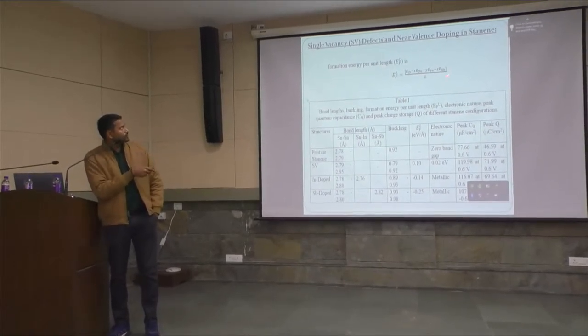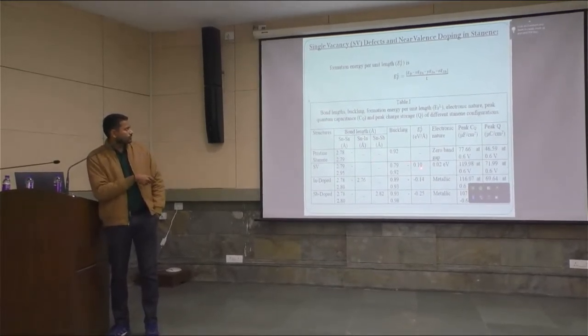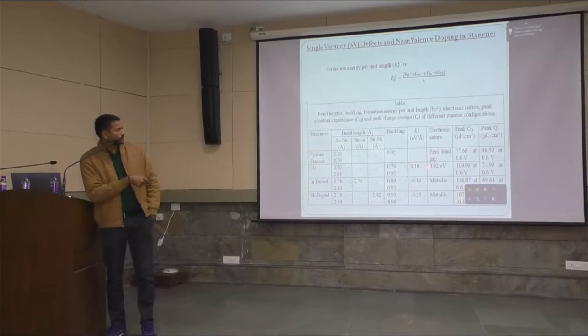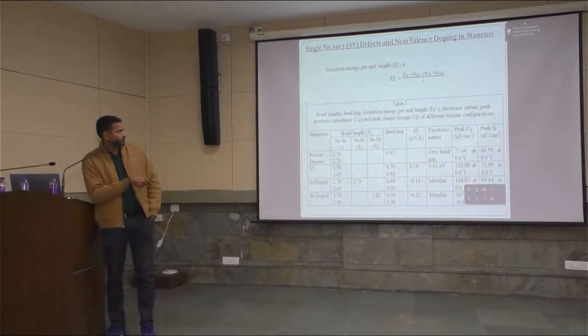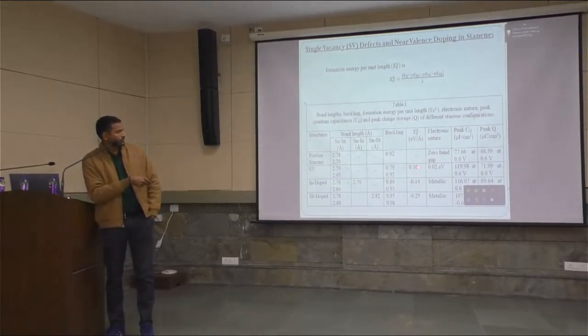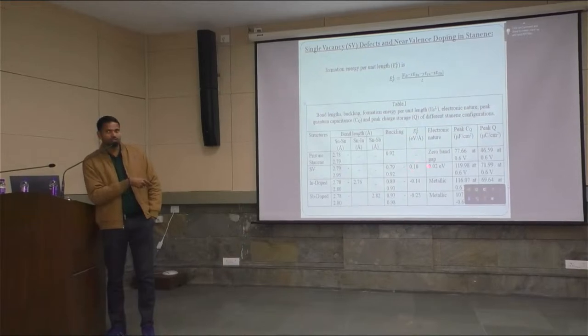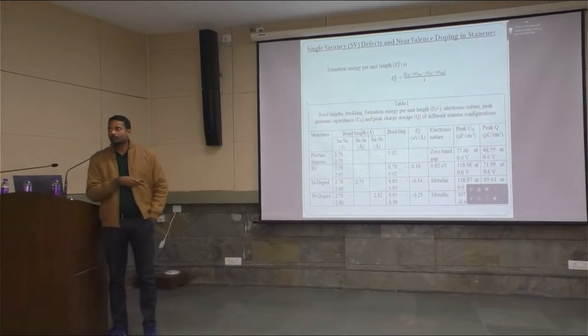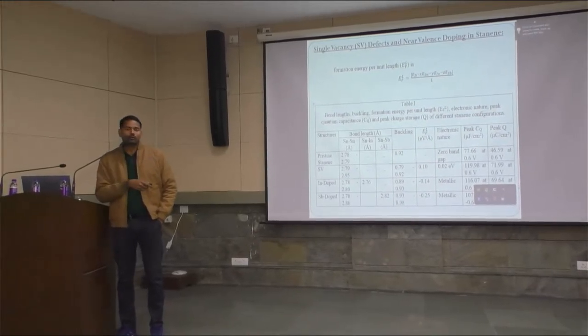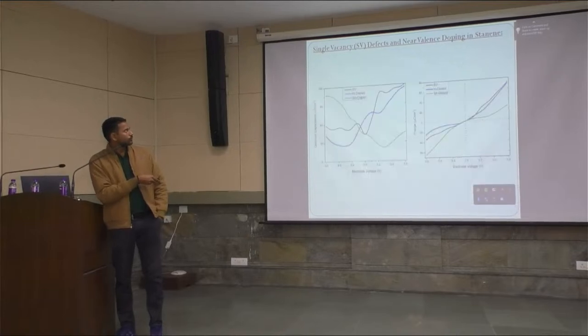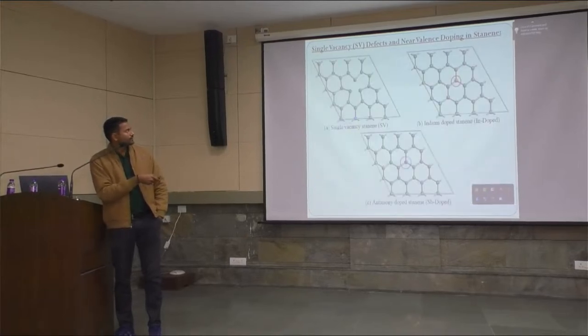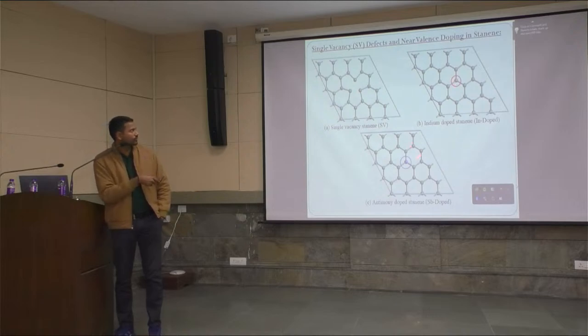when we looked at the formation energy, the stability is compromised, and the formation energy is positive here. It means the structure is unstable. So, to increase the stability and to improve the quantum capacitance, we positioned the near valence dopants, indium and antimony, at the SV site. At the SV site, we have placed indium and antimony.